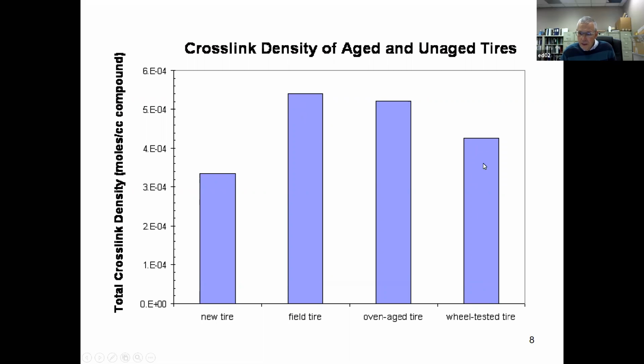So the first thing to mention is that running on the road wheel is kind of an expensive test, already at 7 days, and you're not even close to the field. So the use of the road wheel as a way to achieve a field tire is just kind of way too expensive. The oven aged tire was able in a reasonable amount of time to achieve the properties that are seen in a field tire. And so we look at this as a great thing that's happened, because now we have an artificially aged tire and a field tire with the same crosslink density.